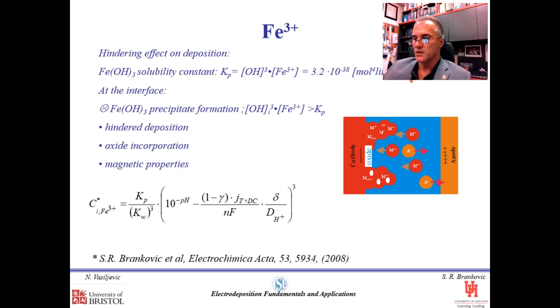Here I give you an expression where we can calculate the maximum allowed concentration of iron 3 in the electrolyte, which if exceeded, the interfacial precipitation of iron 3 hydroxide will start. It's a function of the solubility product for iron 3 hydroxide, the ionic product of water, deposition current density, current efficiency, diffusion layer thickness, and diffusivity of hydrogen ions in the solution. Generally, the same type of expression applies when we talk about other ions that form insoluble hydroxides, which should be well appreciated in terms of designing the process where we do not want this phenomenon of hydroxide precipitation to occur.